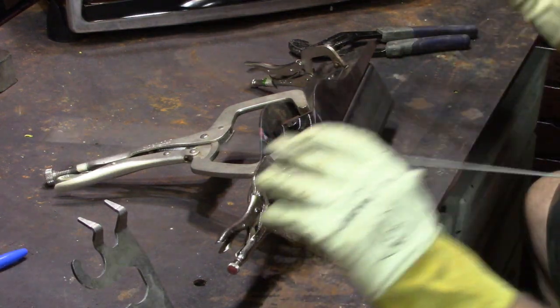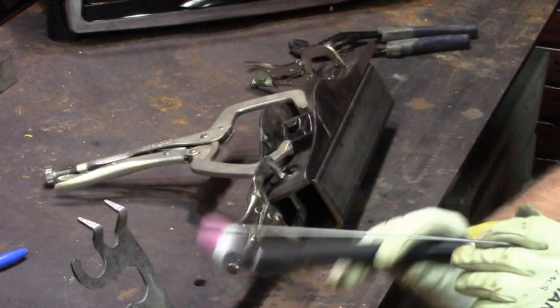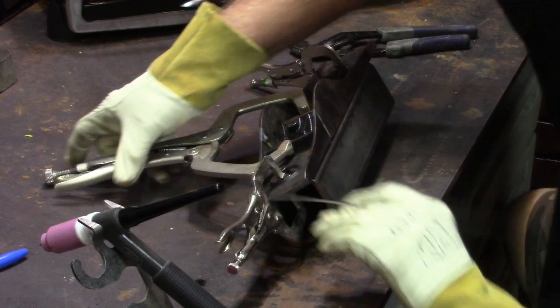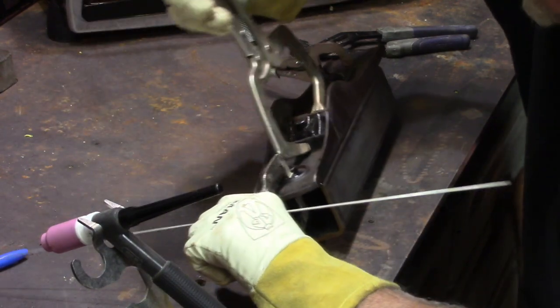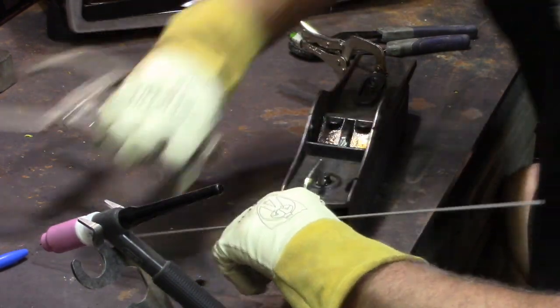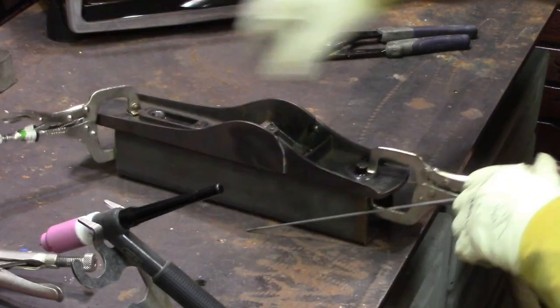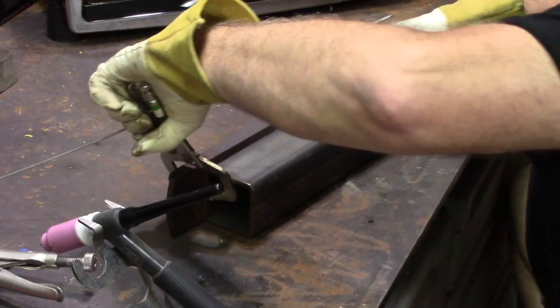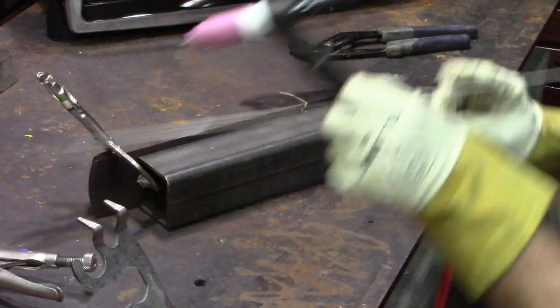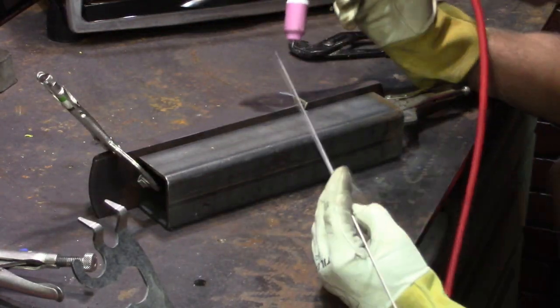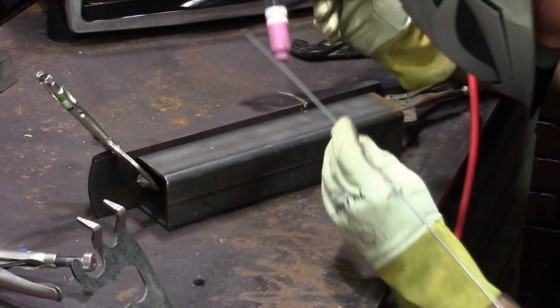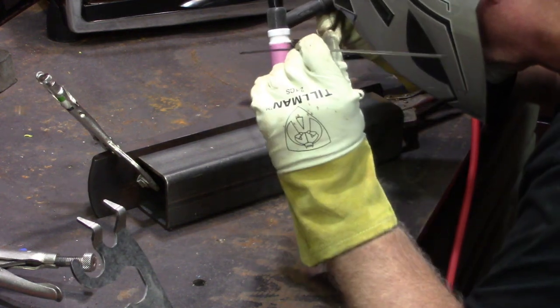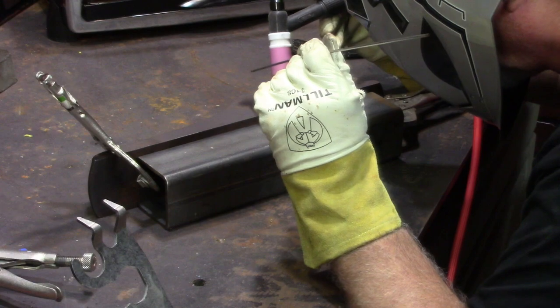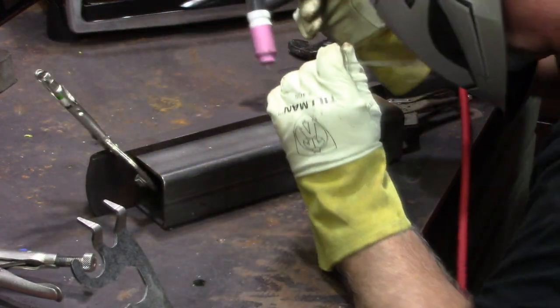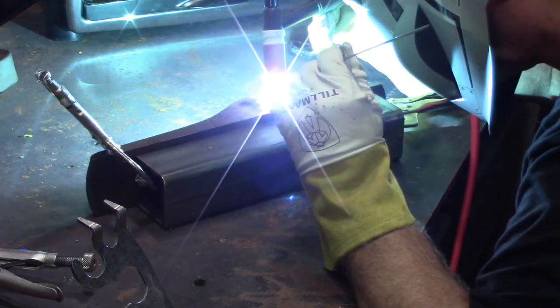Now I've got my tacks on my inner web, and in a minute I can get rid of that clamp which is in my way, and then I can reposition to weld the sides of the webs. The problem here, of course, is I have to do this fairly quick, because every minute this thing is out of the oven it's cooling, and I'm putting heat into it and it's cooling off at the ends, so there's a lot of stresses being built up as I weld this. So I've got to get it welded quick, and I got to get it back in that oven to bring the temperature back up so I don't get any cracks. At least that's the theory.